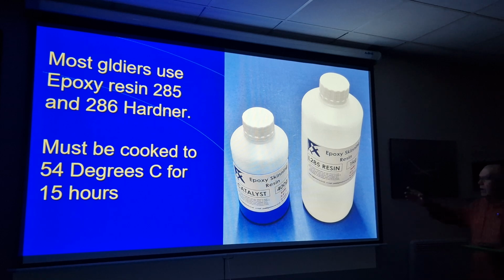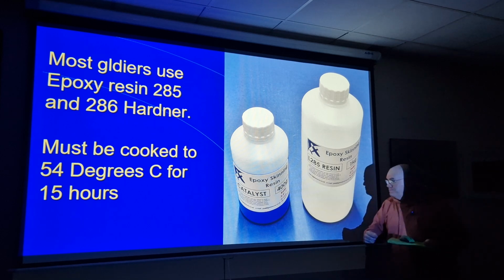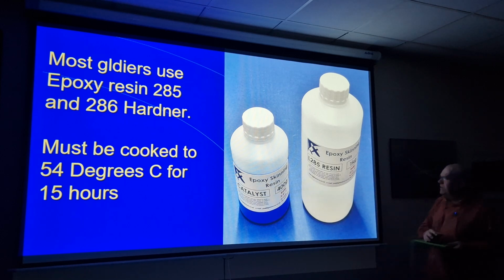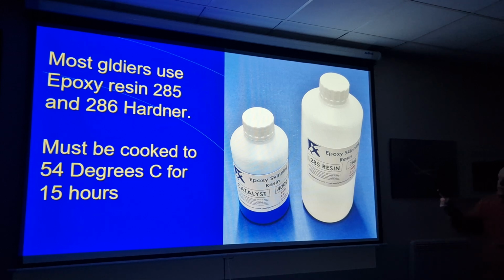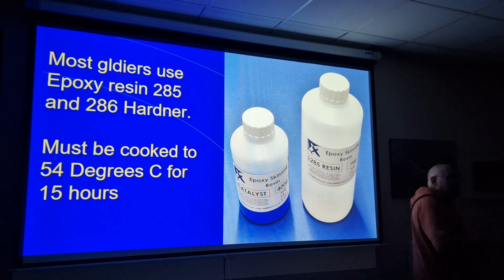And this resin, when you buy it, comes with a use by date. It's about a 4-to-1 mixing ratio, depending on what system you're using. And the resins are only good to the temperature they've been cooked to. So if I was to make a wing in this room here, it's probably at 15, 20 degrees at the moment, and I'll come back tomorrow, it's all set, take it out of the mould, it's fine at this temperature.